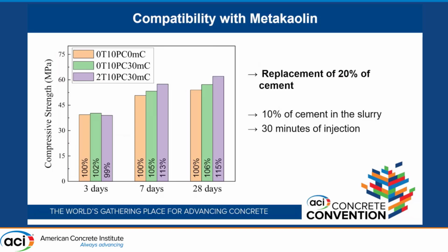For our last case, we have compatibility with metakaolin. In this case, we have 20% of cement replaced. And because metakaolin is more active, we're able to shorten that time. Before we were looking at 90 minutes of carbonation, and now there's only 30 minutes. We also reduce the amount of cement present in the slurry, so it's a little bit closer to what a wash water would look like. So there's only 10% of the cement in the slurry here. And you can see that starting at 3 days, you're just about the same as the control, and then you reach 15% after 28 days.